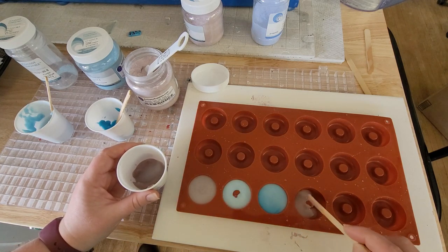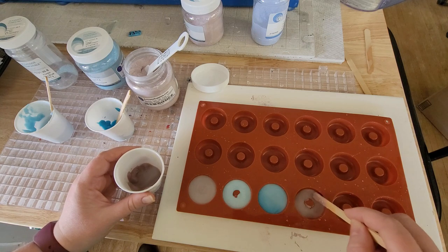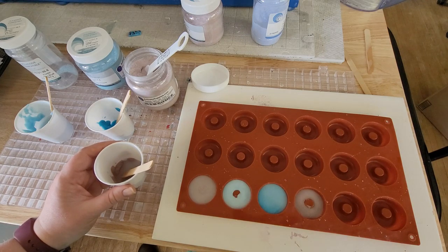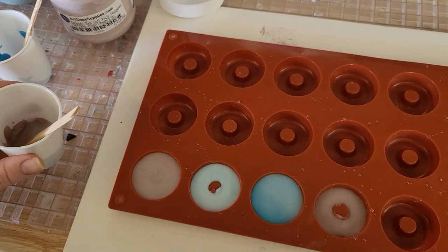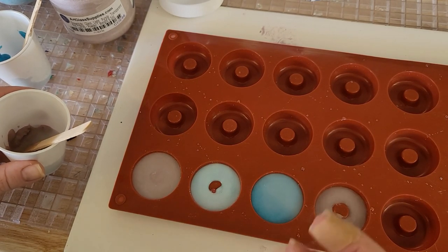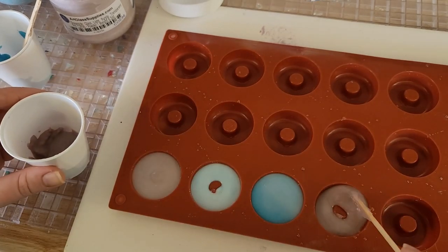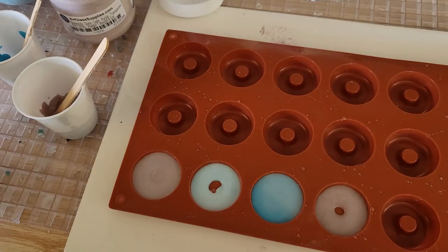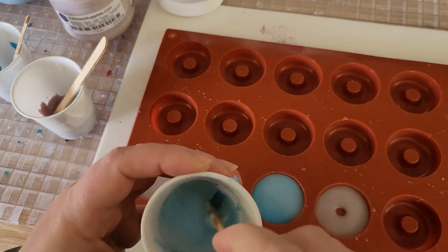And quite possibly even remove a little bit more of the glass to make sure that that center is exposed. Because that's something I thought about, like how there's a little bit overhanging here in the center. Whenever I was doing the moons, I really thought that would be just fine. I really love the color gradient in this one already. But that flashing didn't pull in during the fuse cycle the way that I thought it would, and it left little pokey bits. So this time I'm gonna try really hard to have my stuff be as tidy and clean as possible when we put it into the kiln. Which probably sounds obvious to y'all, but that's a novel concept to me, to do cleanup prep work on the front end.